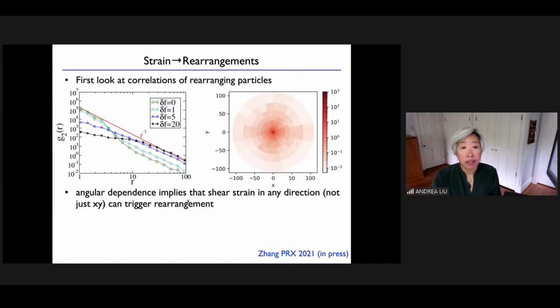All right, what is the next piece? The next piece is what is the effect of strain on rearrangements? So, what we did for this, we looked at the pair correlation for rearranging particles. If I have a rearranging particle at origin, what is the probability that I have a rearranging particle some distance r away? Okay. And this pair correlation function, if I look at it, is actually isotropic in angle. The angular dependence is isotropic. And what that suggests is that it's the shear strain in any direction, okay, not just the XY direction, that can trigger a rearrangement.